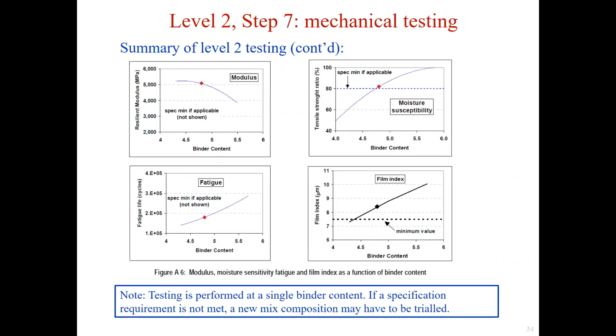The relationships of these properties with the binder content are shown in these figures. We can see that the testing is performed at a single trial binder content of 5%. If the requirement from the specification or guideline is not met, we could adjust the trial binder content by plus or minus 0.5% or 1% and prepare a new mix until the requirement is properly met.